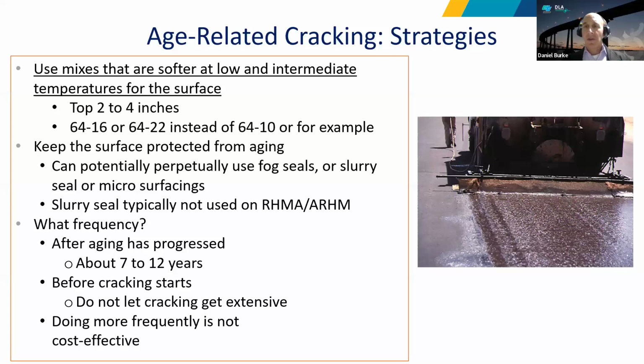Okay, we have a couple more questions here. Will an AC overlay that is 1/2 times the existing AC thickness control the reflective cracking? Probably not. Unless you're talking about an 18-inch existing asphalt layer and you replace the top 6 inches. If you're doing 1.5 inches, 2.5 inches, maybe getting up to 3, it will help. But remember, the age-related reflective cracking is temperature, and the thicker the blanket you put on that, the more you're damping those temperatures. If you've only got a 1.5 inch overlay, it's still getting hot and cold at that crack, and it's doing the expansion and contraction.